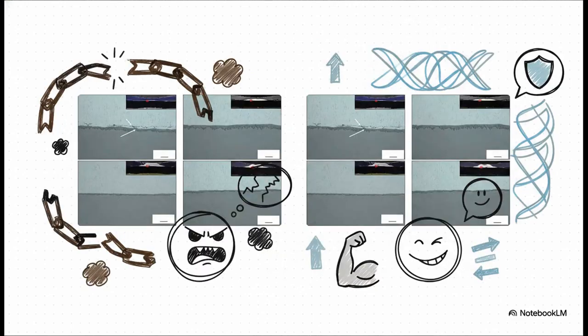And here's what that means in practice. On the left, with the oxide layer still there, you can see how those little unmelted oxide bits get trapped in the weld, creating all sorts of defects and weak points. But on the right, with a clean surface, you get a much cleaner, much stronger bond. That oxide layer is a real troublemaker.